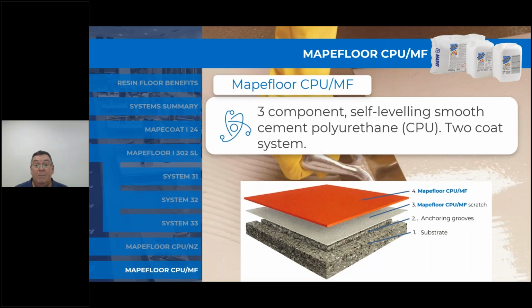So when we look at the Mapefloor CPU MF, it's a 3-component self-leveling smooth cementitious polyurethane. It's a 2-coat system, and it can be applied to a damp substrate again. The anchoring grooves are imperative. This one, the actual Mapefloor CPU MF, can be used as a scratch coat primer. So thinly applied, troweled across the surface as a primer layer, and then the CPU MF is applied over the top of that as a self-leveling floor, spike rolled, as it shows in the slides ahead.